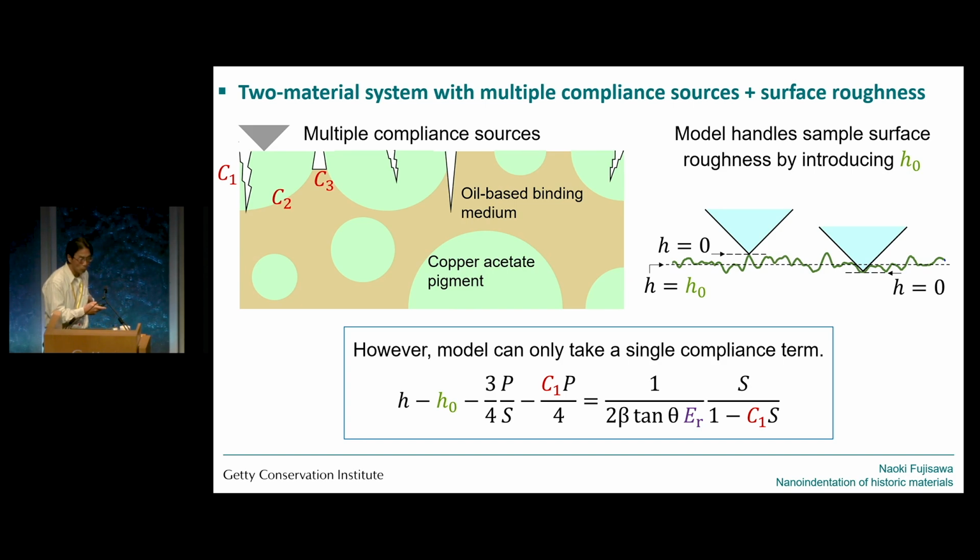And so what we saw in the previous slide is a very complex system, but we believe this complex system reduces to a more simple two-material system with multiple compliance sources resulting from those cracks, and also the presence of more compliant material surrounding the stiffer copper acetate particles.